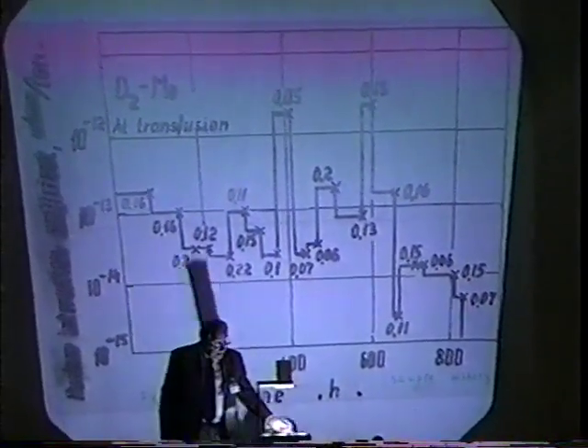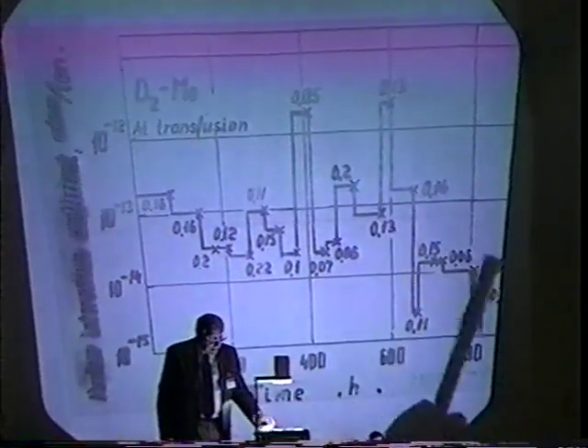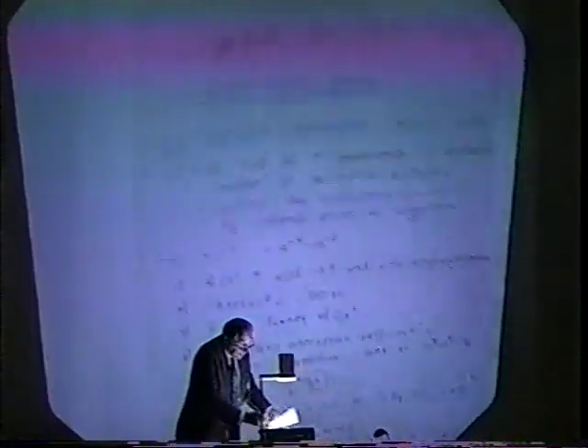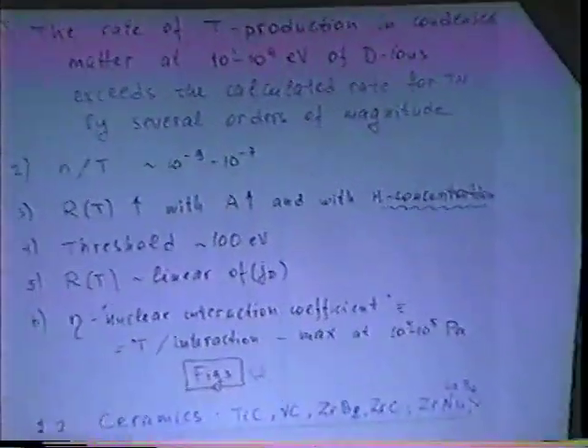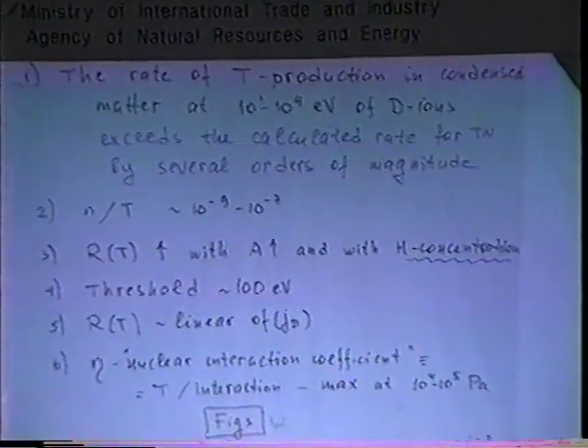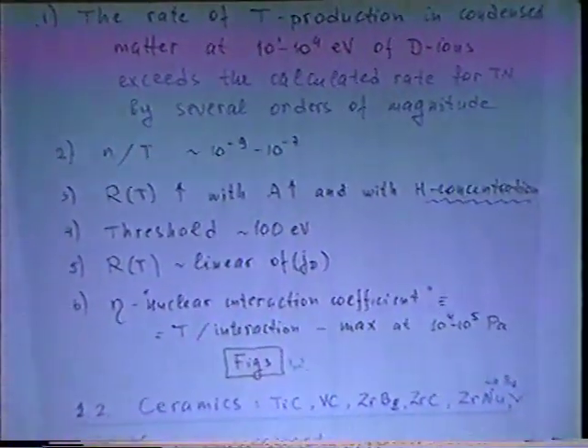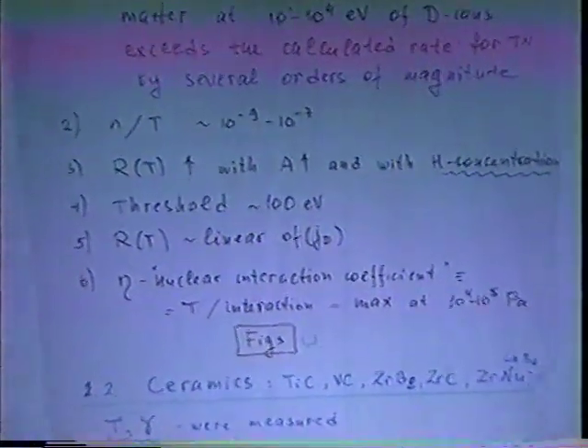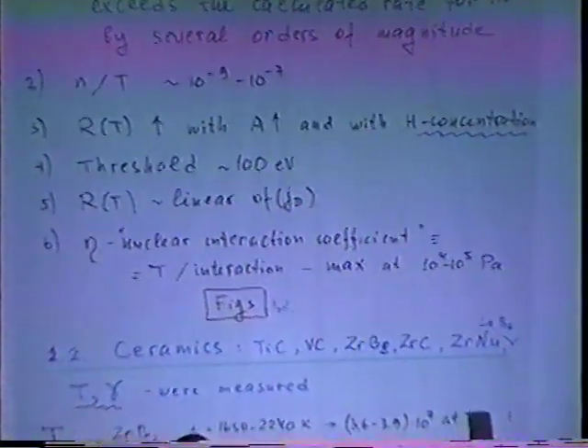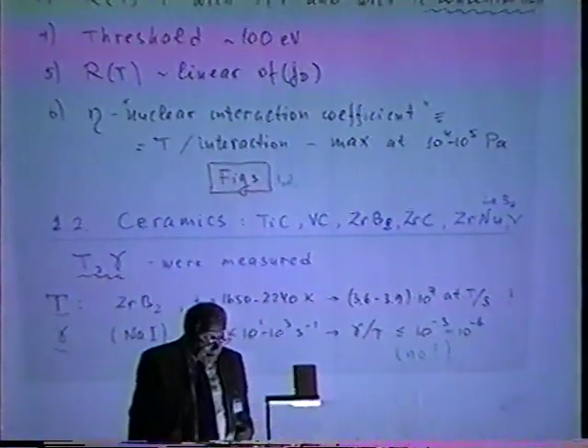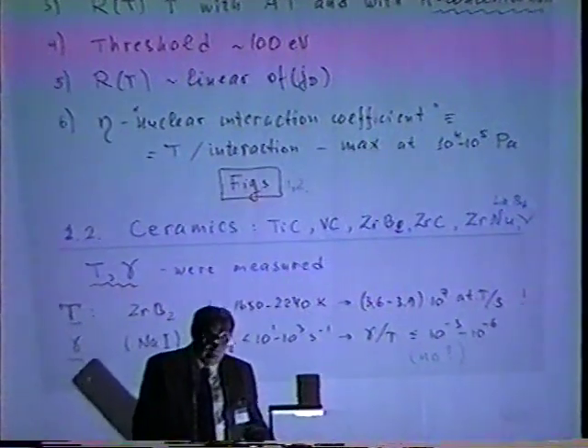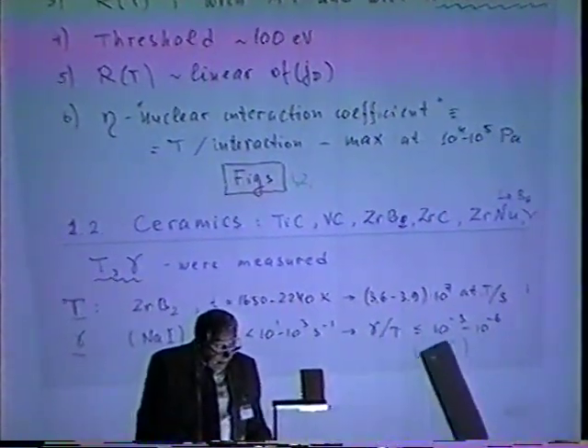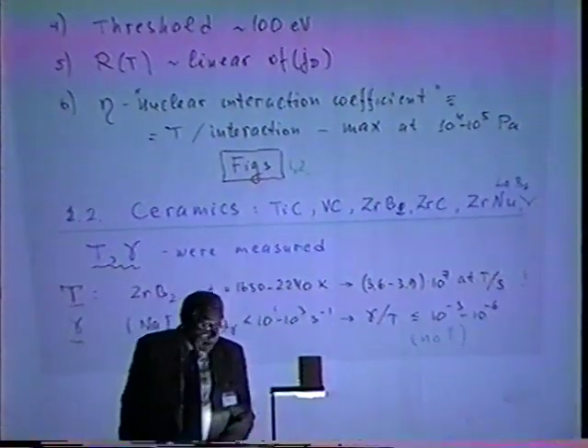And here I also have a picture of the history of one of the samples. It produced some increase, quite easily visible above the average background. This group also presented results received with ceramics. They used this kind of ceramics and tried to measure tritium and gammas. For tritium, they observed for this type of ceramics a rather high signal of tritium production. However, they practically didn't observe any gamma radiation, and their limit on the gamma to tritium ratio is about 10 to the minus 3 or less.